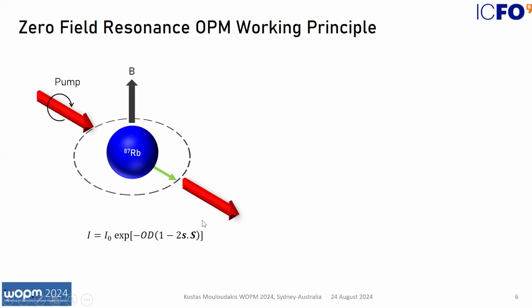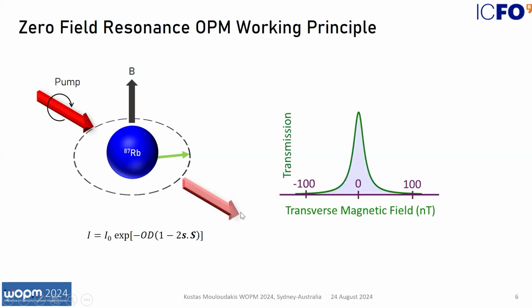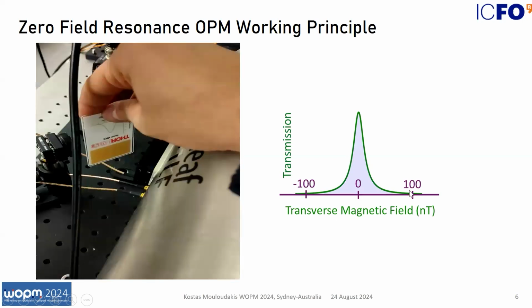And in the presence of the transverse magnetic field, the spin starts to misalign and therefore starts to precess, and the transmission drops. And if we want to describe this schematically, we see the optical transmission as a function of the magnitude of the transverse magnetic field, and we have at zero field a transparency window of a few tenths of nanotesla, which drops roughly as a Lorentzian at higher magnetic fields.